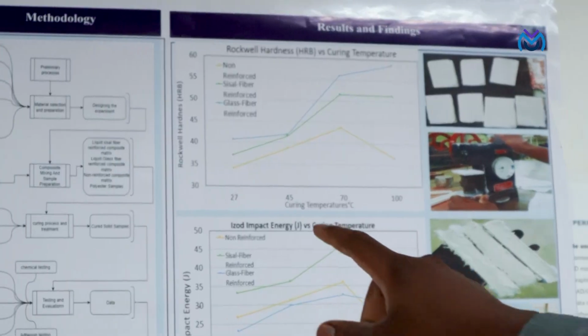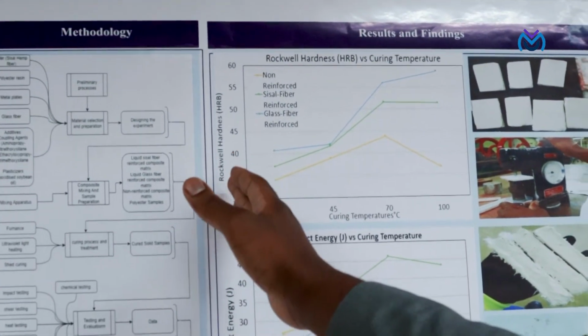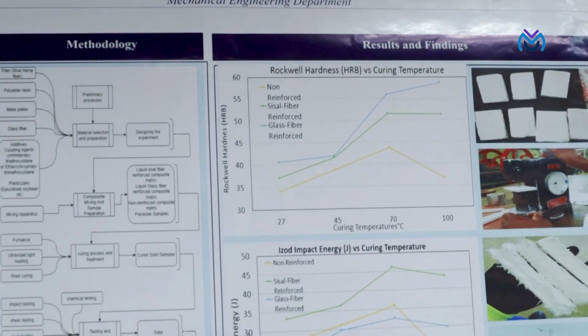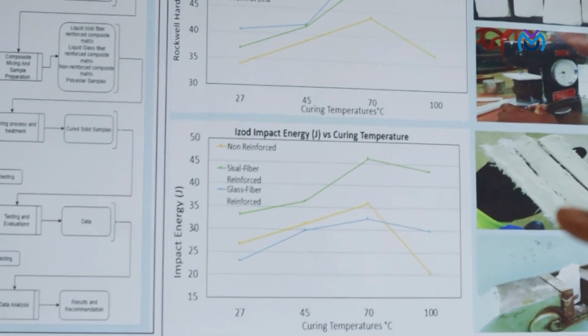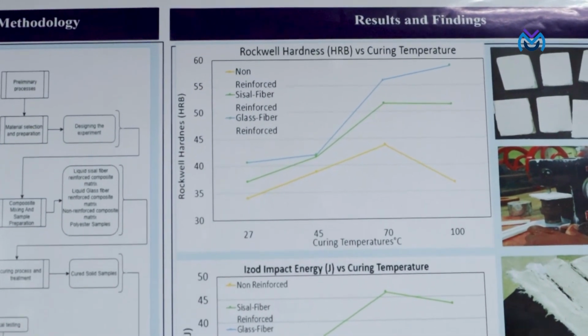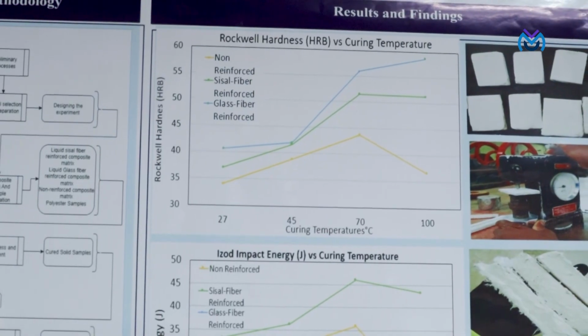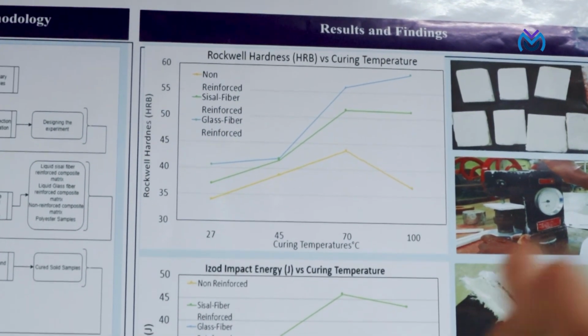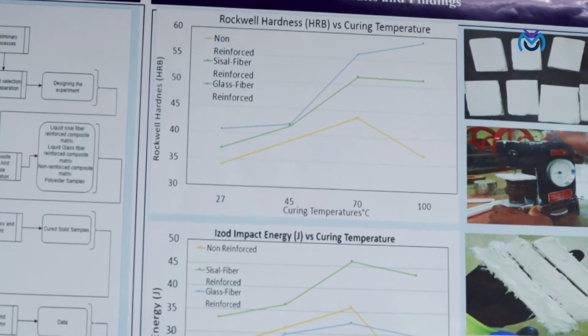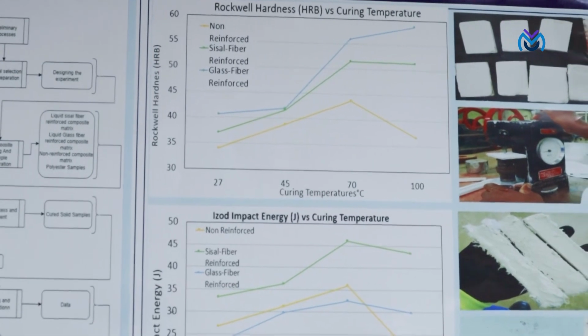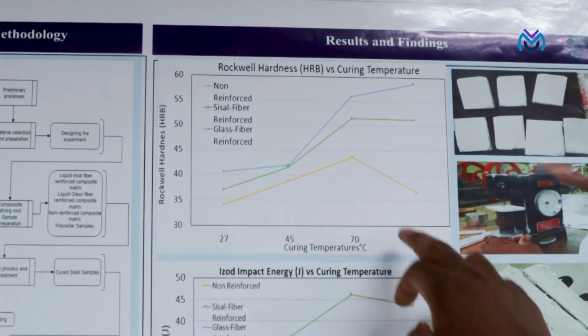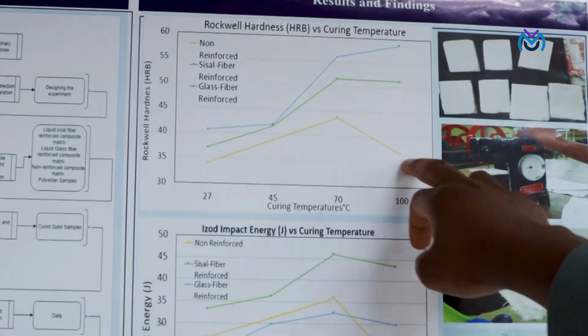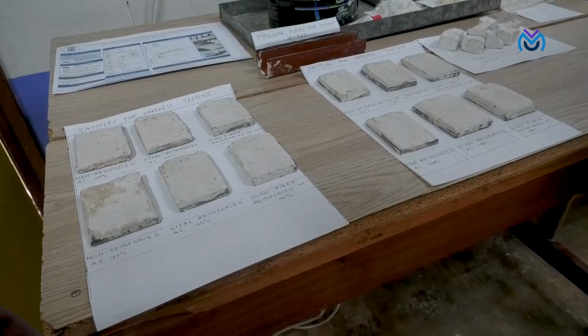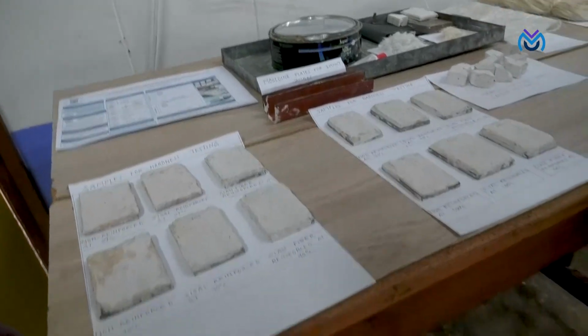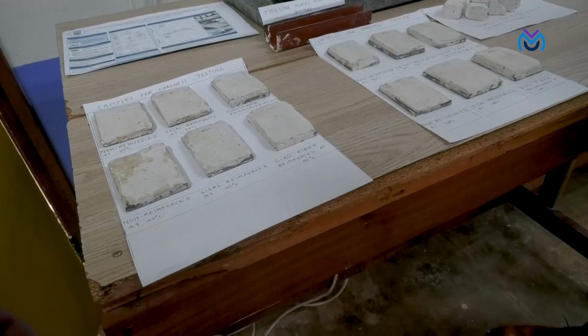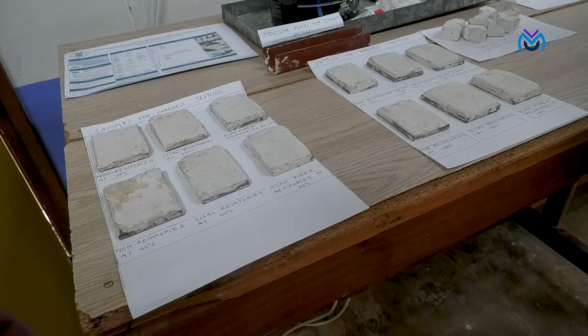The glass fiber is the one with the blue line. Here are the hardness results versus the curing temperatures. The results for hardness for glass fiber were higher than all the other results. Sisal fiber, however, was competitive with the glass fiber. From 27 to 70, all of them were rising. But above 70, the non-reinforced composites were going lower, as we can see here, without any fiber, which shows that under hardness testing, the body fillers are prevented from indentation. If we add fibers, they will prevent dents from coming on them.